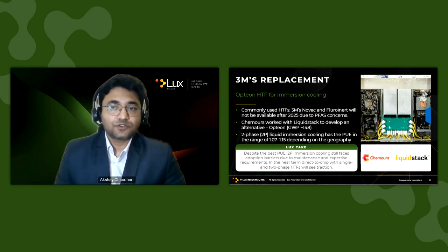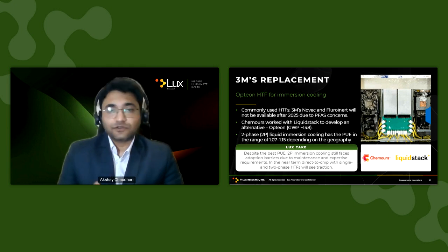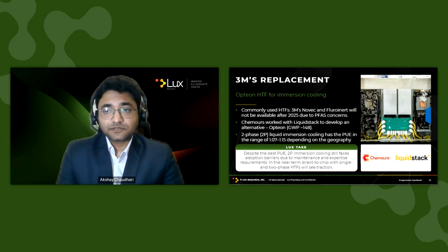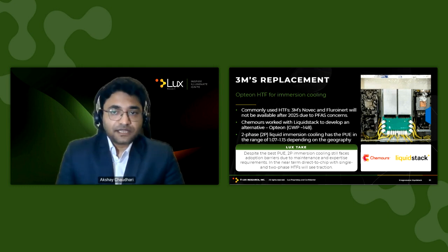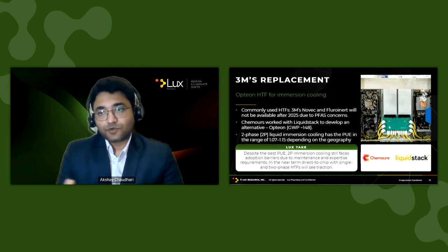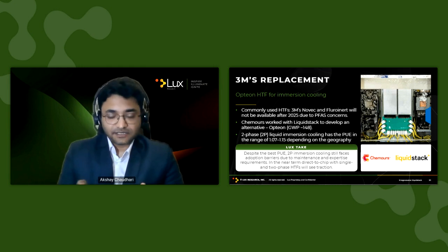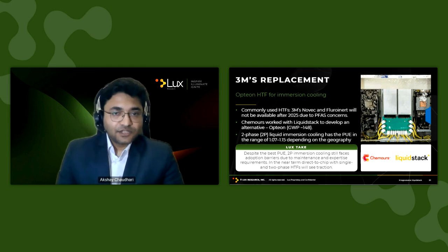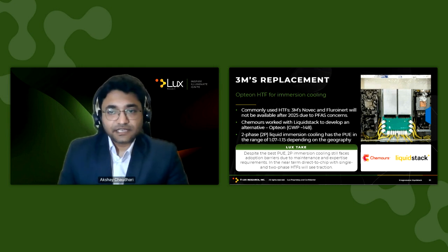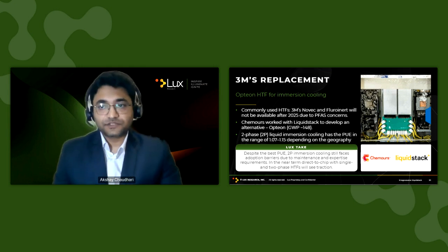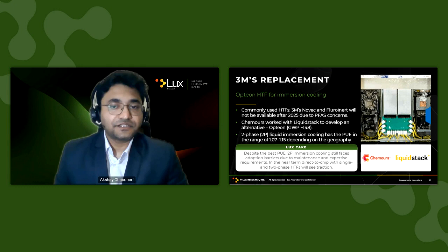And the solution, Opteon, has a global warming potential of 148, and they are even further working on reducing it. It has already gone through some testing, and the initial results show that the power usage effectiveness, PUE, with Opteon ranges from 1.07 to 1.15, depending on climate conditions and geography. So while this PUE is significantly lower compared to the other liquid cooling solutions and also the air cooling solution, there are several challenges here.